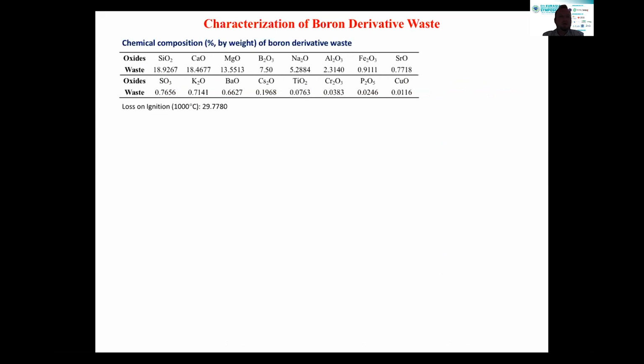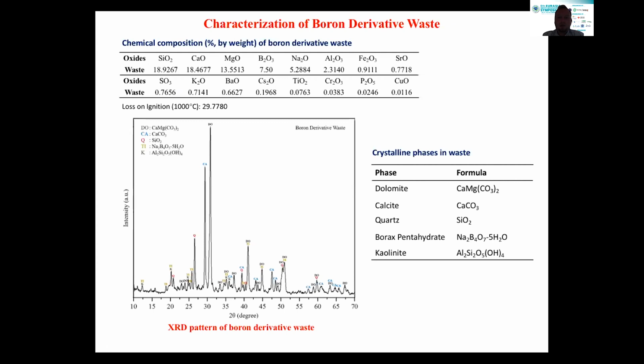So what is the boron derivative waste? The chemical composition of the boron derivative waste is mainly silicon, calcium, magnesium, boron, sodium, and aluminum elements, and there are also trace elements in the structure. So what about the crystalline phases in the waste? According to XRD, X-ray diffraction analysis, dolomite, calcium magnesium carbonate, calcite, calcium carbonate, quartz, borax pentahydrate, and kaolinite can be found in the waste. The major phases are dolomite, calcite, and quartz. You can see that these phases include carbonates. With heat treatment, we can remove these carbonates, and then we can provide reactions between these phases.